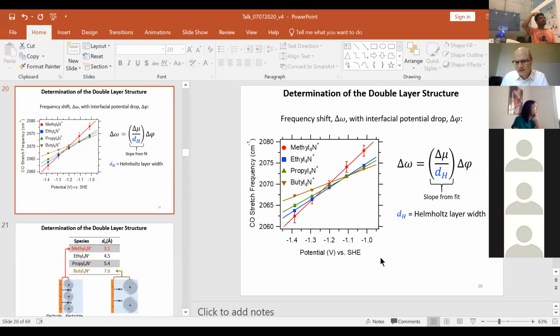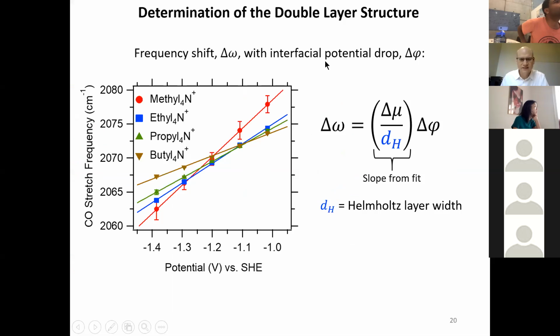This one. So you see that's shifted, and that has to do with two things. So this tetramethyl ammonium is shifted up, and you can also see the error bars are quite large. The other error bars actually show very good reproducibility. But for the tetramethyl ammonium, there's a bit more error. And we have some spectroscopic evidence that suggests there's probably a more direct interaction between tetramethyl ammonium and our surface compared to the other cations, and that manifests itself in two ways.